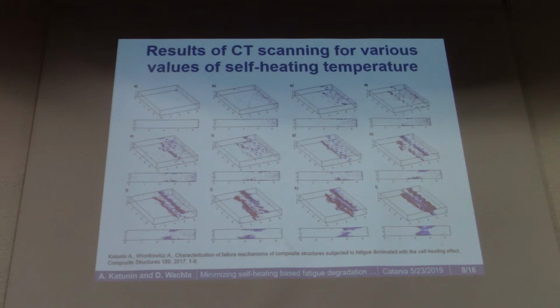Finally, on specimens prepared in the same manner, we did computed tomography tests just to look inside, to check what is going on inside, how these cracks propagate and what the damage mechanism is. These plots are reconstructed from CTs. Blue color is a crack, red color is delamination, and it started from 55 degrees Celsius. At 60, you can observe some cracks in the material, and then it propagates from the surface to the middle plane of the structure.